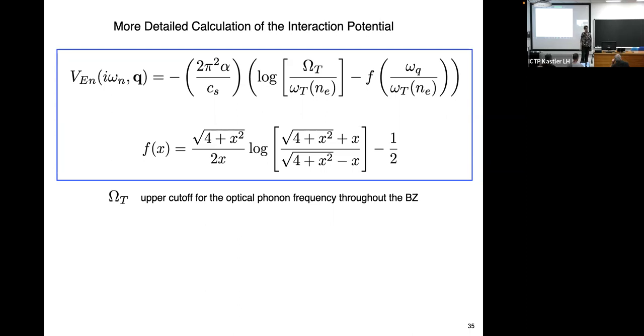That's actually an interesting point, particularly because one of the things we've been thinking about, which is related to Andy's talk, is that everything here was in the nearly polar phase, but you can also go into the polar phase. Then instead of P, you have P plus average P, which means your TC will be a function of strain. So you could really boost your TC in the system. Susanne Stemmer at Santa Barbara has some work on this which shows TC to be higher, but I actually think you could really bring it up. And that might be a test for this kind of mechanism. But I should say that we were just happy to get a TC that seemed reasonable, but I see what you're saying.